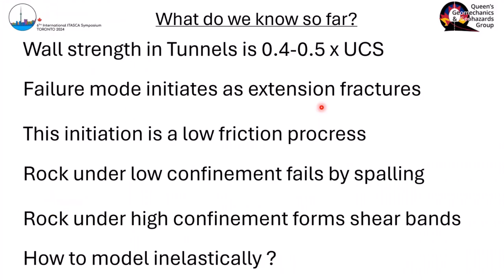So what do we know? Well, wall strength seems to be around 40 to 50% UCS. That corresponds to what we see in the lab as the onset of dilation. We know failure modes initiate through extension fractures. It seems to be a low friction process, and I say friction in the general sense of confinement dependent strength. It may or may not be friction, we don't know if it's friction or something else. I have a lot of ideas, but that would take another talk. We know that rock under low confinement fails by spalling. If you increase the confinement, you eventually get to shear bands.